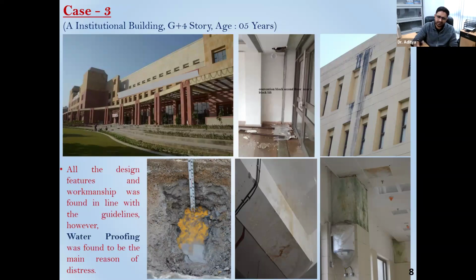And because of this, the main reason here was the poor waterproofing, and because of this, in the entire slab portion, if you look toward the terrace, this entire PCC of 6-8 inches was removed, and it cost them around 4 to 5 crore just to repair this once again. So that was a problem, but it's good that the problem was identified at the beginning of its age, and therefore not much deterioration to the building has been caused. And after successfully doing the waterproofing properly, the building is now doing pretty good.